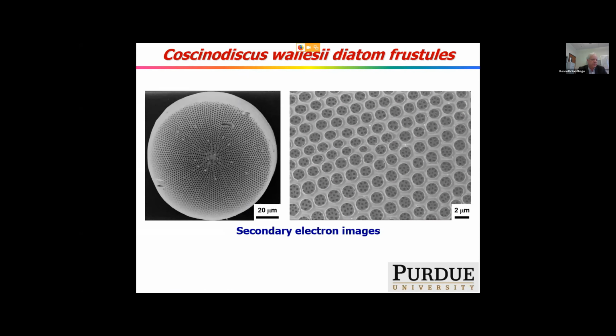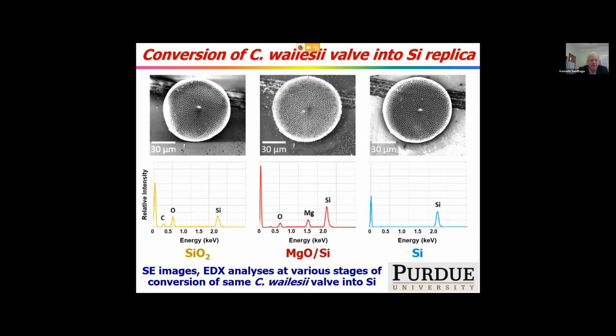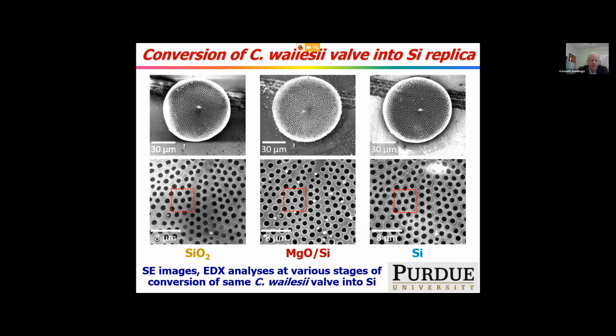Here's a diatom called Coscinodiscus. It's a disc-shaped diatom that has this rather intricate pore structure. So on the left, you see the overall image of the diatom and the EDX pattern showing that it is silica. The same frustule in the middle, now converted to MgO and silicon, and on the right, to silicon by dissolving the MgO away. We made a higher magnification image of the valve.